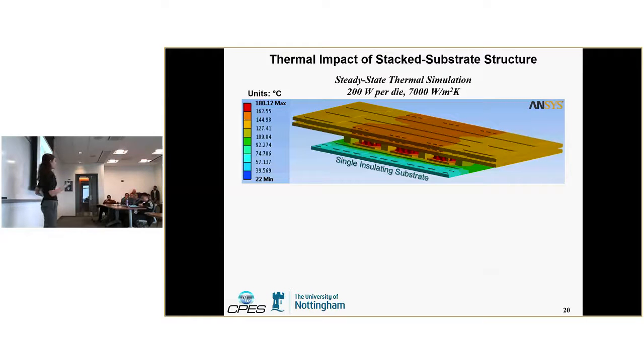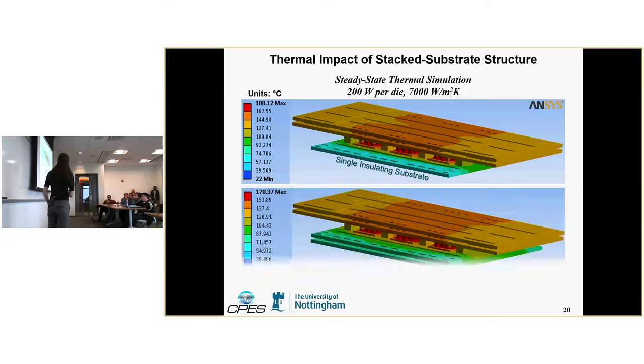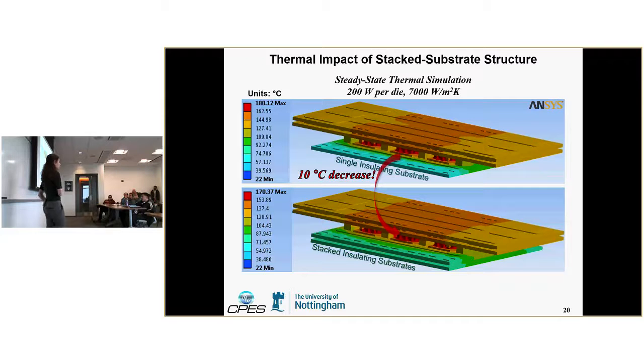But again, as we mentioned before, your thermal interface usually comes from the bottom, the main location for your heat extraction. So we need to make sure that by adding that second ceramic substrate, we're not significantly hindering the thermal performance. So this is a 3D steady state thermal simulation. These here are the semiconductor die. This is for the single insulating substrate case on the bottom, and the peak junction temperature is about 180 degrees C. Then when you stack 2 substrates together, the peak junction temperature actually decreases by 10 degrees C to 170.